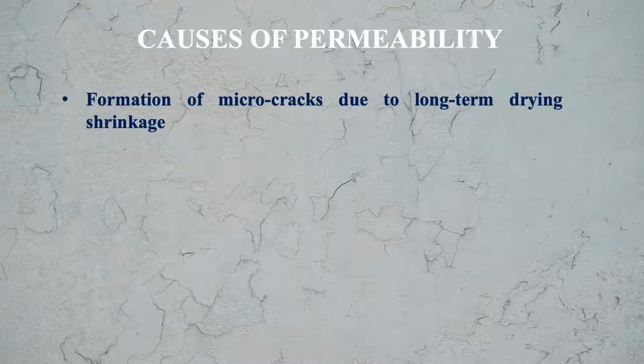So what are the reasons for that? Because we saw in the table that with age the permeability is decreasing, and at 8 days it is almost comparable to the permeability of a rock like granite. So where from this permeability in the concrete is coming? So let us see the causes of permeability. The causes of permeability includes formation of micro cracks due to long-term drying shrinkage.